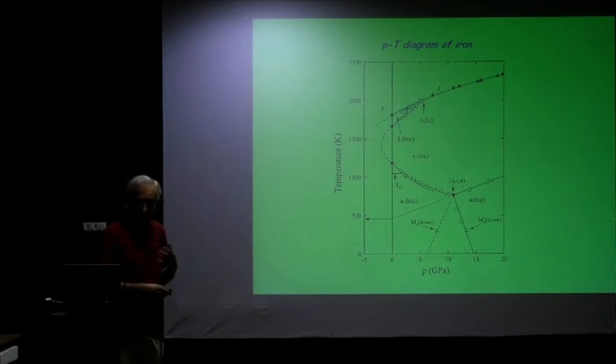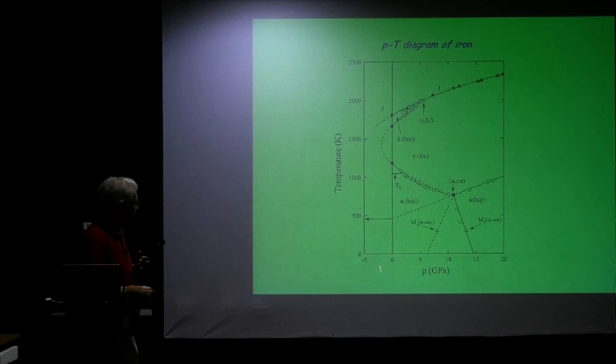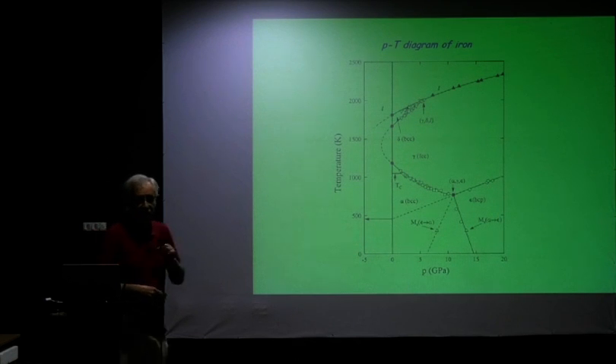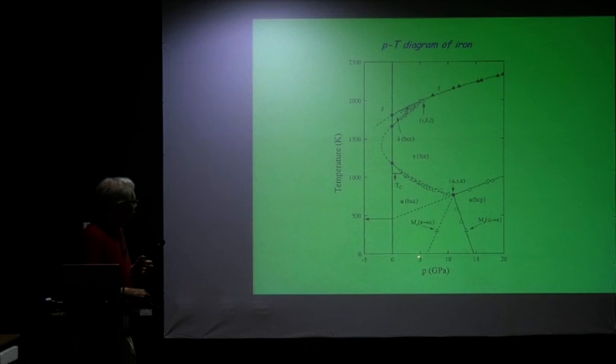Now let's look at the phase diagram of iron. So we have lots of phase transitions here, okay? So we have the temperature dependence. That is the critical temperatures as a function of pressure. What happens when we vary the atomic volume in iron? That's why we're looking at the pressure. So we have here various phases. At zero pressure, as we had seen, we have here a BCC phase. This is the Curie temperature of BCC iron. And then we come into the FCC phase. And then here, this is also BCC iron, and then we go into the liquid phase.